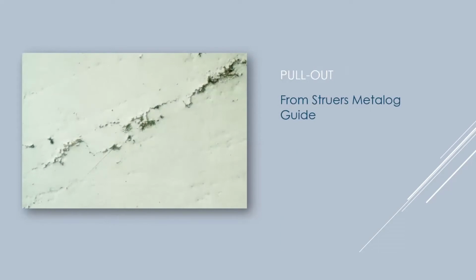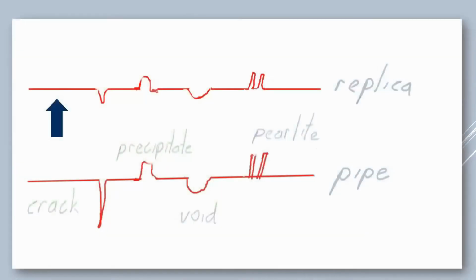The other problem too is that cloth with nap is another artifact that ASTM doesn't like, is we tend to pull out carbides and precipitates and inclusions very easily with that cloth with nap, and then we're left with something like this. You really couldn't tell if that's a crack or whether I pulled something out of the steel, and now it's going to make interpretation very difficult. So ideally, I have cloth with nap, but I don't use it that much unless it's really dirty outside. So this is what we do.